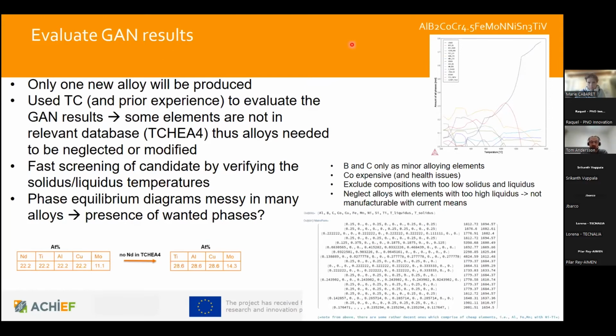So finally, evaluate the results. There was a long list of different candidates produced with the GAN, and we made this fast screening for those with this Thermo-Calc or CALPHAD tool. And for that, solidus and liquidus temperatures were a bit different than for this rule of thumb that was used for the training of this neural network. So the list was shortened quite much.